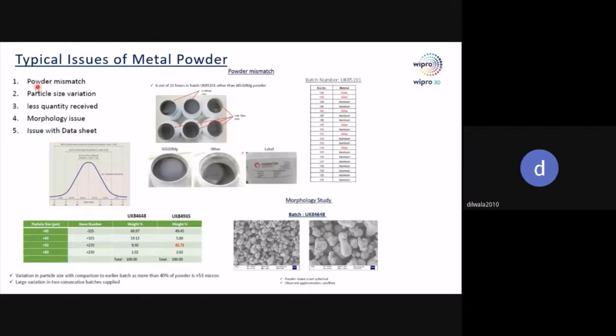So this is a typical example, powder mismatch. Say we have ordered some 20 boxes of AlSi10Mg powder. When we received the powder, we noticed that all the boxes are weighing 20 kgs. However, when we open the powder, 14 boxes are fully filled and 6 boxes are half filled. But when you weigh them, both show 20 kgs. So with this, we were sure that we had received some other material instead of AlSi10Mg.